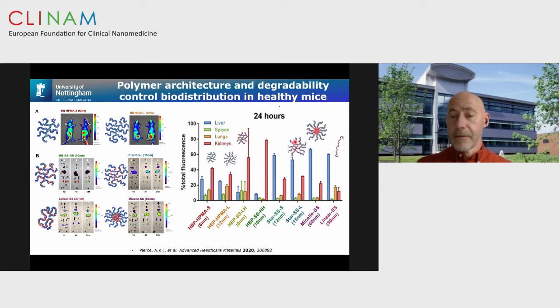So on this side, we have perhaps what one might expect, slightly larger polymers going to a greater extent into the liver. And these are what you might expect with sink organs based on their size and also their shape. Now, this linear polymer almost certainly assembles into kinetically trapped micelles, which are about 30 nanometers. But you'll see there's a gap in the middle where there's two polymers, which I haven't shown, and I'm now going to show their cartoons.